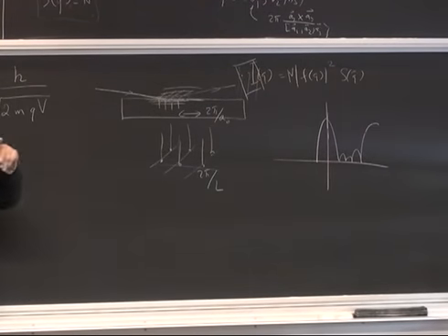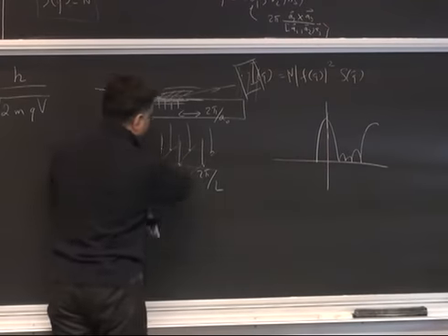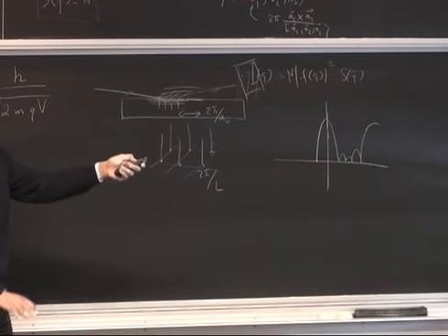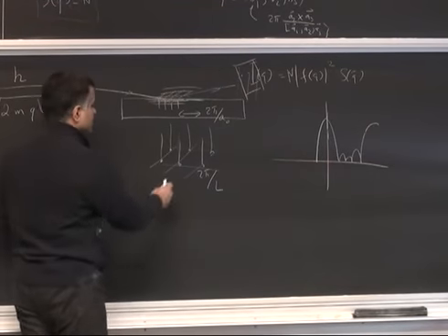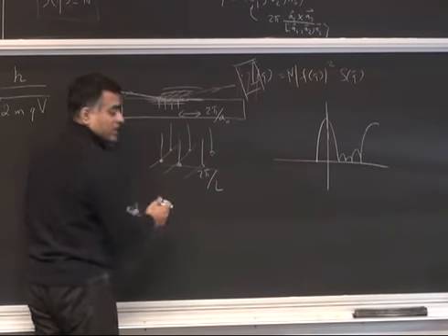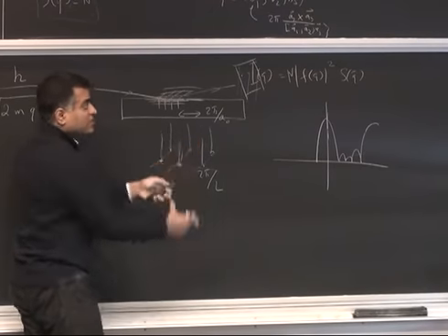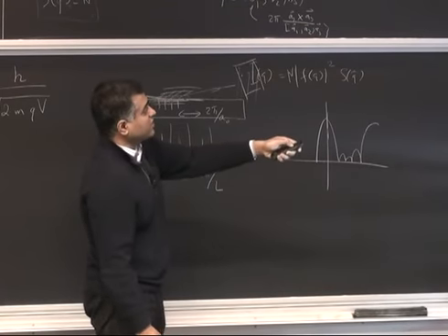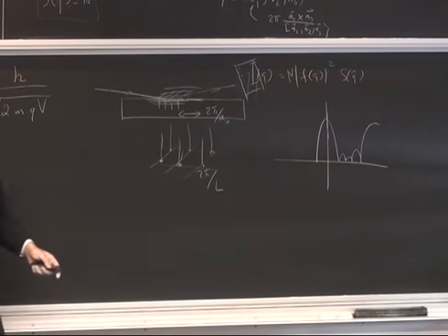If, instead of a perfectly atomically smooth 2D layer, you had some surface roughness, meaning a layer which is only partial, not all the way 2D, there is some disorder in this plane, so this line becomes a little bigger in diameter. As a result, where it intersects, instead of a very sharp point, you get a line, a streak.